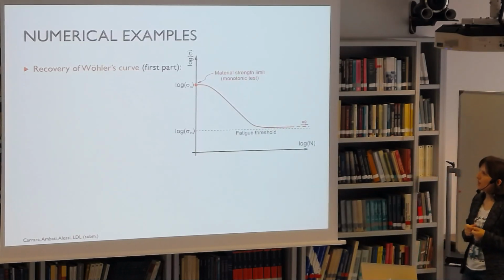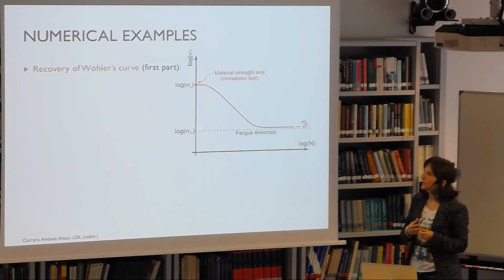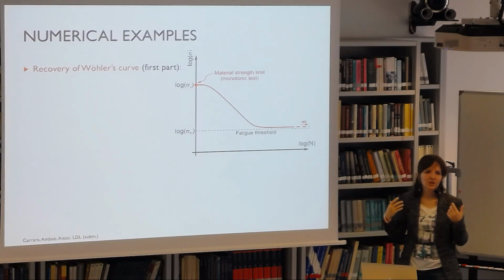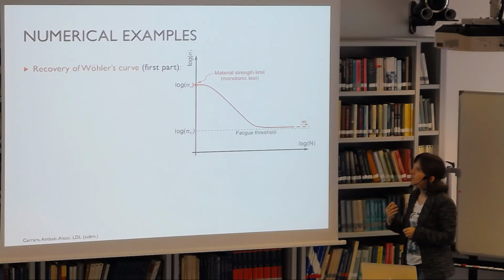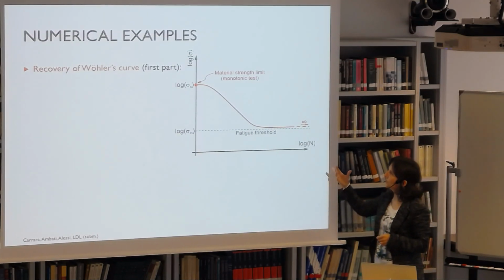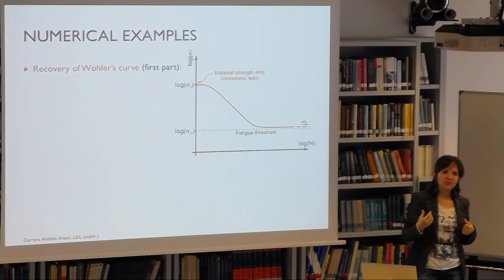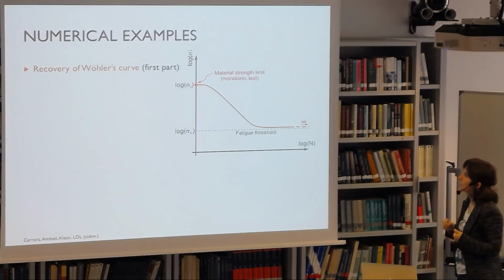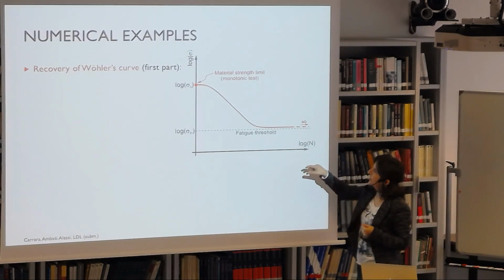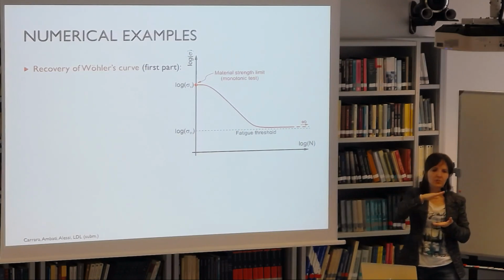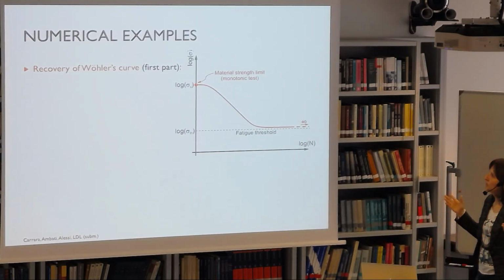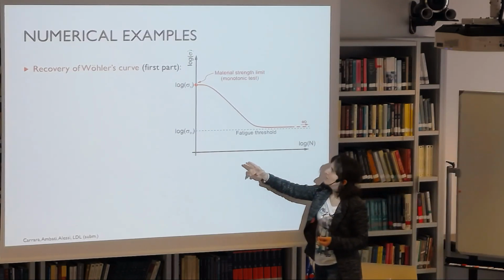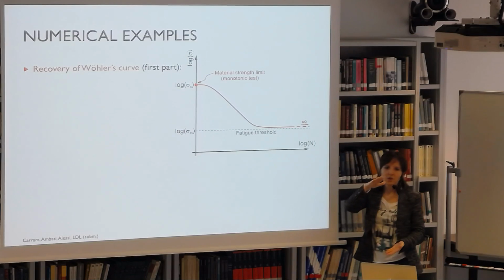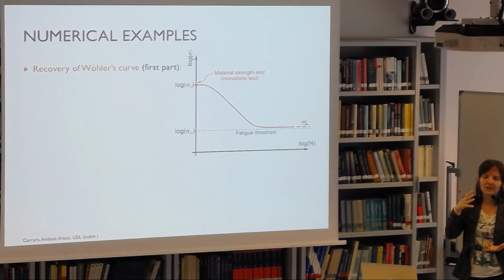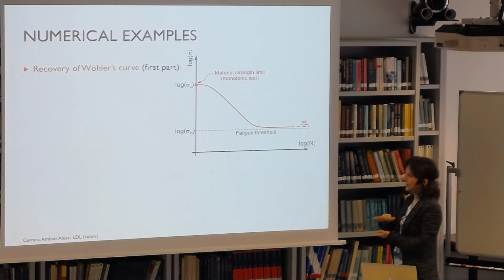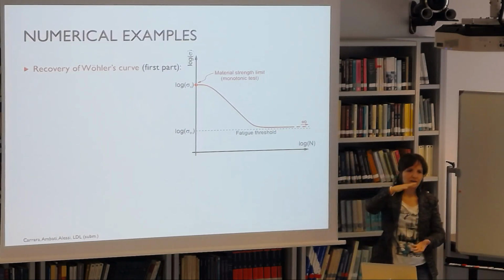Now, another feature of fatigue behavior that we wanted to recover is the oldest information on fatigue that was available to engineers already in the 1800s, the so-called Wöhler's curves. These are curves that, as opposed to Paris results, are case dependent, so specimen dependent. Here you have the number of cycles on the x-axis and the amplitude of the applied stress on the y-axis. And what you expect is that, of course, if you have only one cycle, then you can apply at the maximum the tensile strength, the static strength of the material in a monotonic test, and as you increase the number of cycles, or as you decrease the applied stress in cycles,